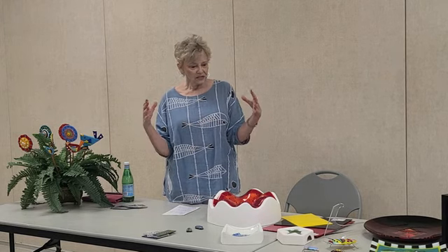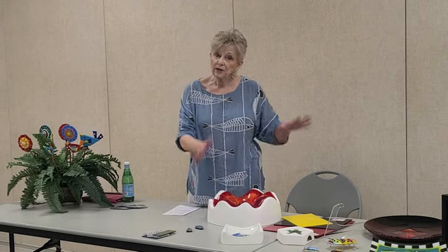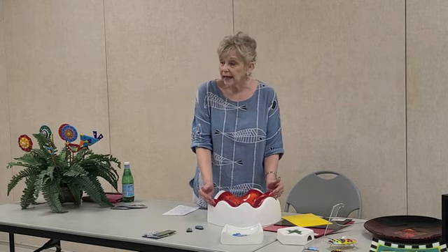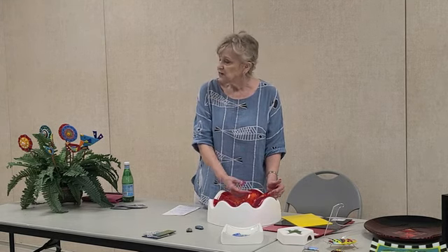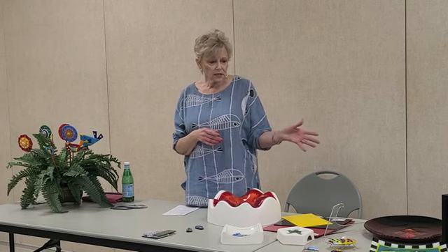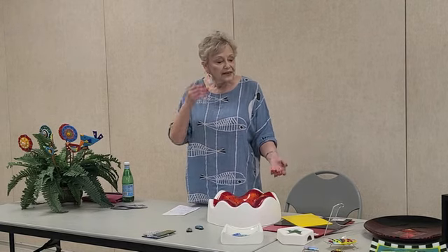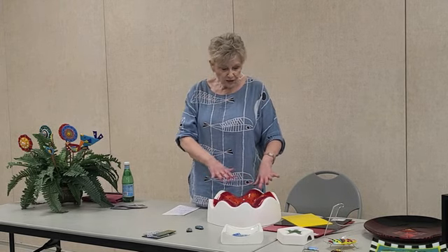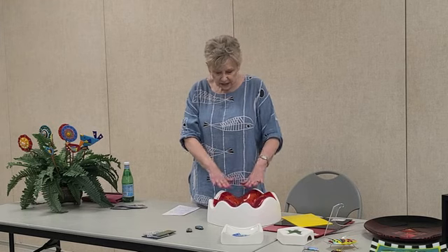Anyway, once I got the big circle all flat and pretty, I put it into a mold like this. Then you go through the whole process again, except this time it doesn't take nearly that high a heat to get it to fall down into that shape. So you can go slowly, because you don't want it to crack going up. Lots of thermal shock issues. You determine probably on this one about 200 degrees an hour, then take it up to say 1200 and hold it there, and you keep checking. Eventually you learn how long, and it becomes that nice shape.